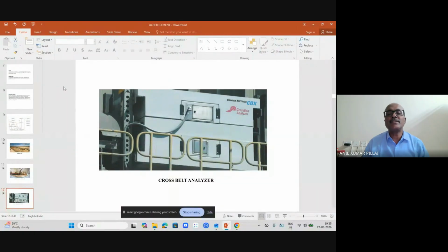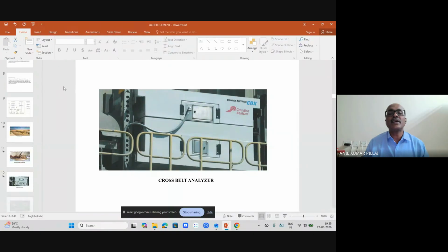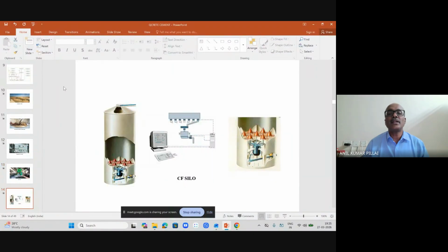The cross belt analyzer is a kind of online analysis of the various raw materials. You can find out what kind of composition is there, and necessary changes can be made online itself. So this is the mechanism that is there to have better control over the quality of the cement that is coming out. This is the raw mill, and you have the CF silo, the continuous flow silo, where continuous homogenization takes place. Again, the objective is to bring down the variations in the raw materials.